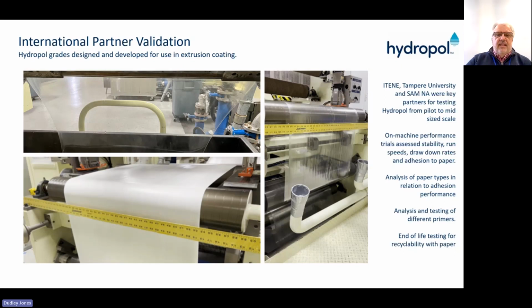For extrusion coating, we developed this material in conjunction with a number of people: ITENE, Tampere University, and SAM North America, where we took the resin and moved it from pilot to mid-scale size. This was done last year or the year before, where we have a full size line, 900 millimeters wide in SAM, that is capable of running Hydropol if people want to do pilot tests. We can also run that in the Nordics. We also have a facility for pilot trials in the Nordics, and potentially here also in the UK.